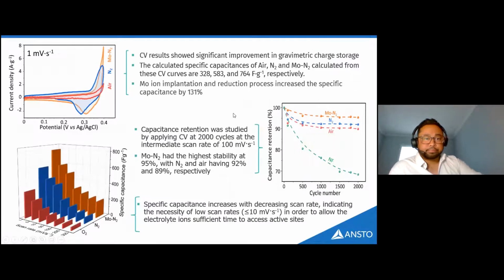Next slide, please. Okay, so the figure at the top left is cyclic voltammetry, which showed significant improvement in gravimetric charge storage. The calculated specific capacitances were 328, 583, and 764 farads per gram for the air, the nitrogen annealed, and the molybdenum implanted sample respectively, representing about 130% increase in specific capacitance for the sample with the molybdenum ion implantation over the nitrogen annealed sample alone. The bottom left plot further highlights the enhancement in specific capacitance for the molybdenum implanted sample, and also with decreasing scan rate, which indicated the necessity to allow the electrolyte ions sufficient time to access the active sites.